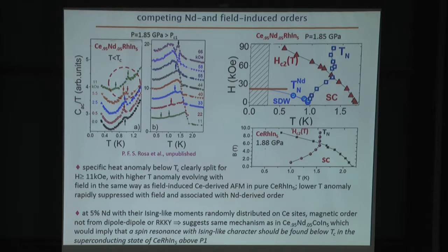So again, the question is, what happens to this neodymium-induced magnetism in an applied magnetic field? And we show some of those data in these panels here. Here we've applied a pressure such that the magnetism due to cerium is absent, and we see only this small anomaly due to the presence of neodymium. And now these are at a fixed pressure, and we're increasing the applied magnetic field. What we see is that this weak anomaly begins to split at a field of around 5.5 kilogauss and 11 kilogauss. This anomaly clearly is split.